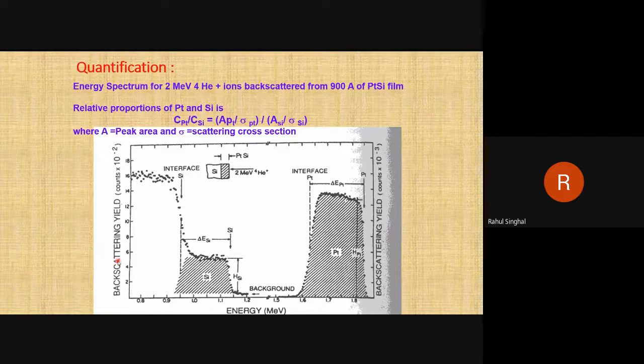So from this raw data, just by knowing the position of the peak, you can tell which element is present. Just by finding the FWHM of the peak, you can tell the thickness of your film. And just by calculating the area of the peak, you can easily tell the elemental concentration of that element. So simply, it's a play of some data.